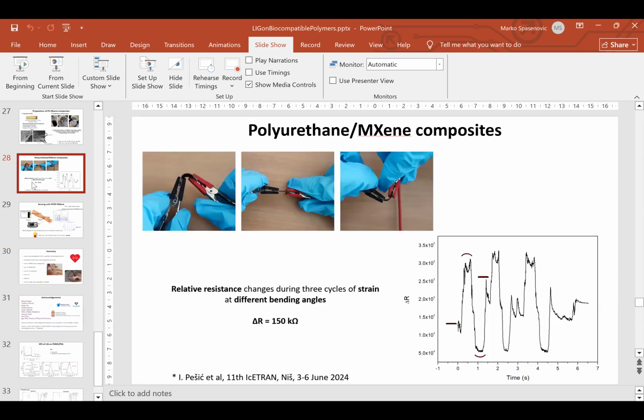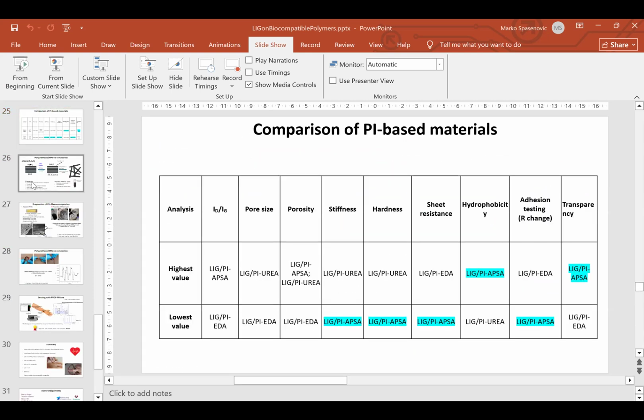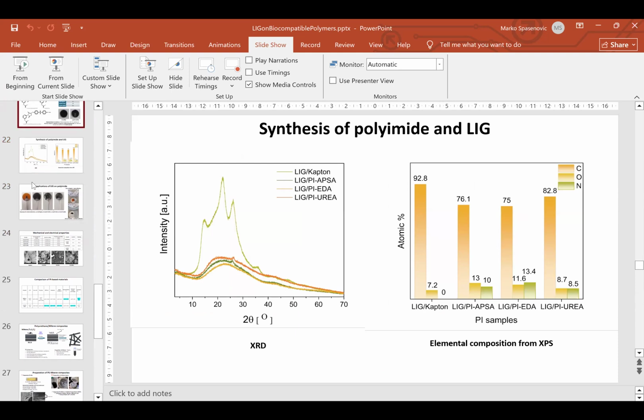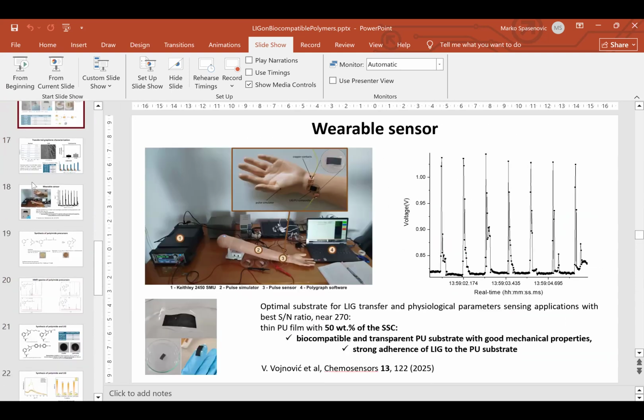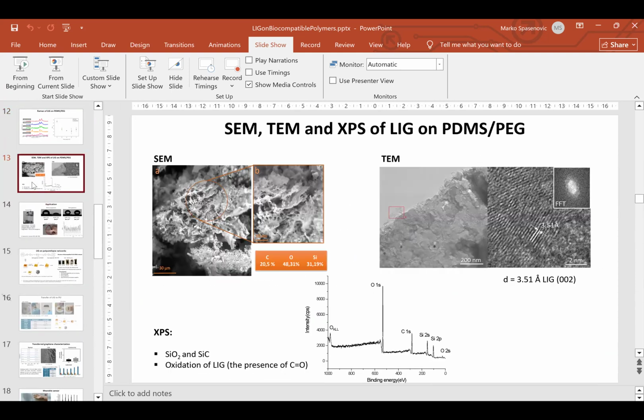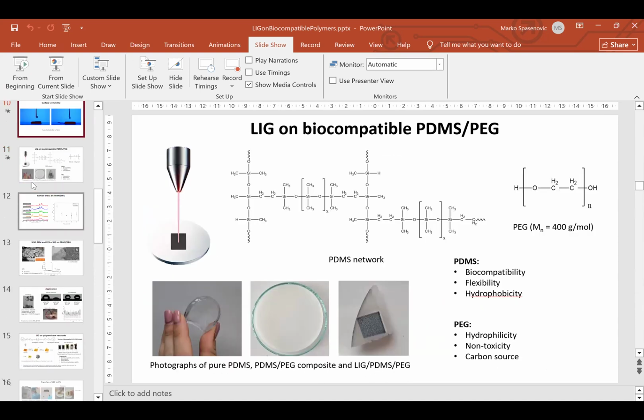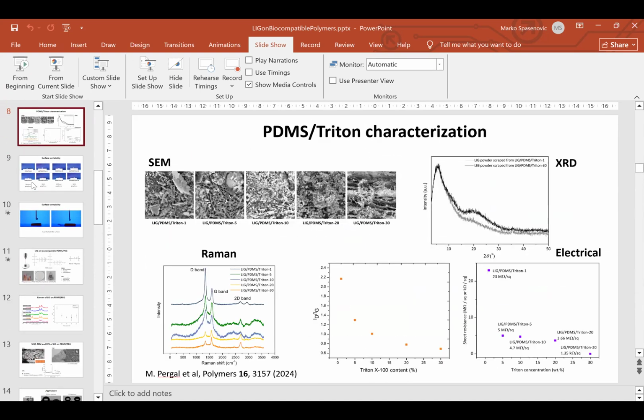So this one comes from Faizan. In the case of the Triton slide, the Raman spectrum shows a higher D-band intensity compared to the G-band, indicating a higher level of defects. However, for highly ordered graphitization, the D-band needs to be smaller. Also, we expect XRD peaks to appear around 26 degrees and so on. However, in the slide, the peaks were shifted. Do you want to comment on this one?